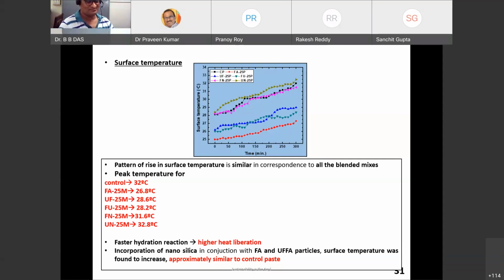But for the last 1.5 years we have been completely dumb, actually, because the labs are closed. You know how much time is going with COVID. So I don't have the measurement of the core temperature. But I am sure that for this nanoparticle admixed cementitious composite, the core temperature will be much higher than the control. I am very much sure. We will measure it at some point, if the situation improves, and I may be in a position to tell you the core temperature of nano silica admixed in this form. So that is a disadvantage.